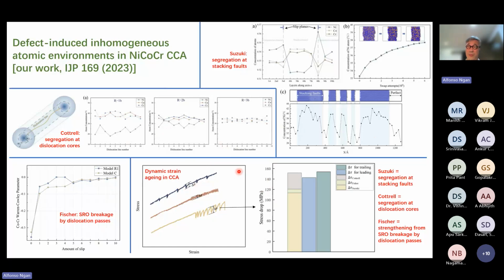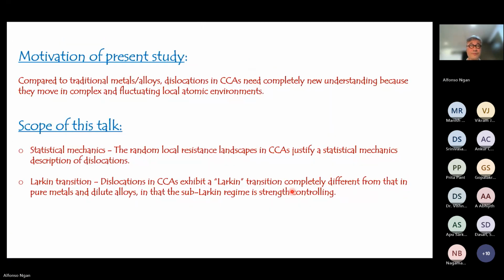So in this paper, we analyzed out of these various mechanisms which one is more dominating. And for this particular alloy, it turns out that the Suzuki, this stacking fault segregation, turns out to be the most dominating, which is the yellow color in here. So in this bar, we are breaking down the contribution of the several mechanisms. So the yellow contribution is from the Suzuki. And then the second major one would be from Cottrell. And then Fisher turns out to be a very small contribution. Well, that's only for this alloy. For other alloys, the situation may not be the same.